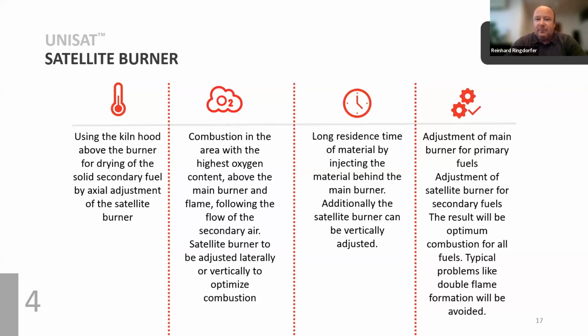The thing is that beside a main burner that is capable of adjustment in any direction, with high burner momentum for good mixing, you also need a satellite burner, which also needs to be adjusted. So it's not a fixed pipe anymore. The satellite burner is designed for axial adjustment, horizontal and vertical adjustment, to find the optimum position to mix the particles you're injecting with the main flame, so that the primary air jets can mix the secondary fuel with the primary fuel, and you have a combustion of both fuels together.